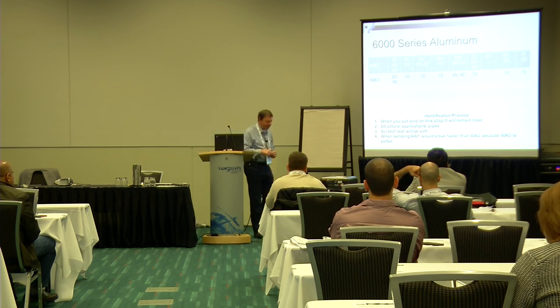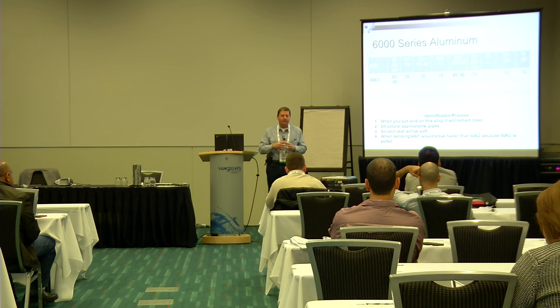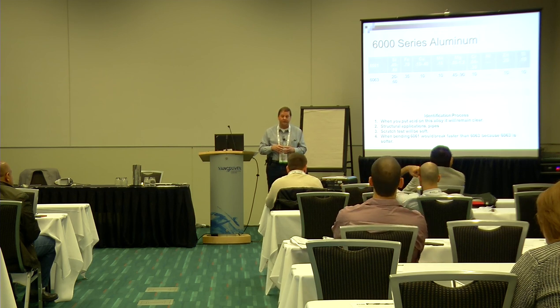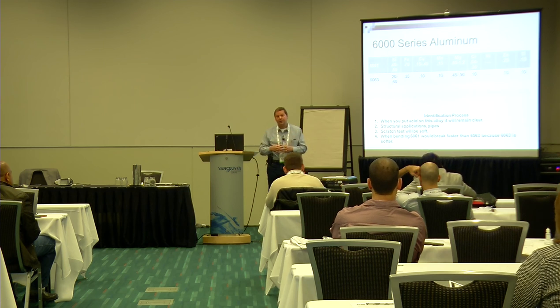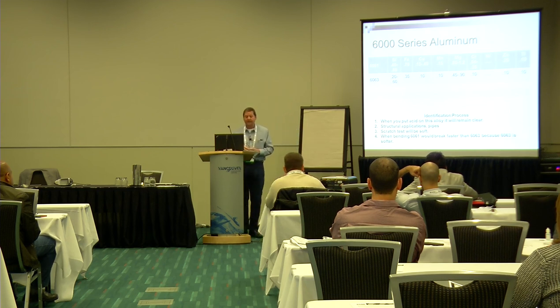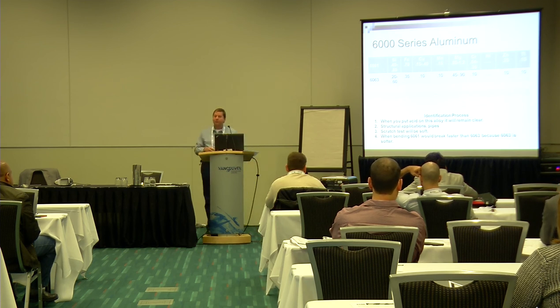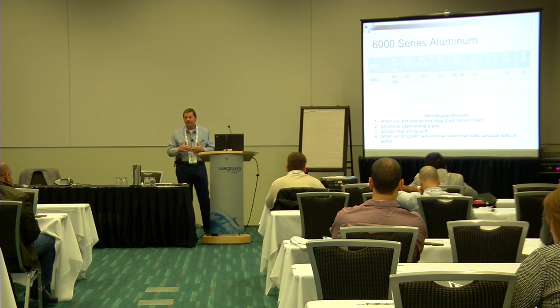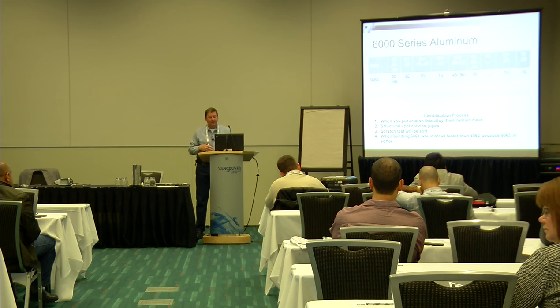6000 is a very important one because in your scrap yards, you're going to get 6061 extrusion, you're going to get 6063 extrusion, and you're going to get 6061 that's not extruded. The question would be, what's the difference between the 61 and the 63? It's going to come down to the chemistries again. If you look at the iron, that's the biggest one right there: 6061 iron is 0.7 versus 0.35 for 6063. Even though it doesn't seem like a lot, that's a lot of difference in that scrap. So that's the big one there.